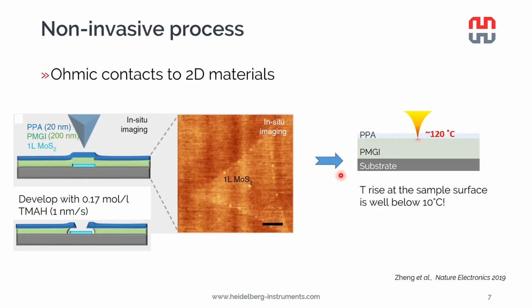It's worth mentioning that during this process, the tip apex temperature is reaching only about 120 degrees Celsius, which is enough to decompose the PPA. And we estimate the temperature rise at the sample surface to be well below 10 degrees Celsius. So it's a very gentle process for sample fabrication.